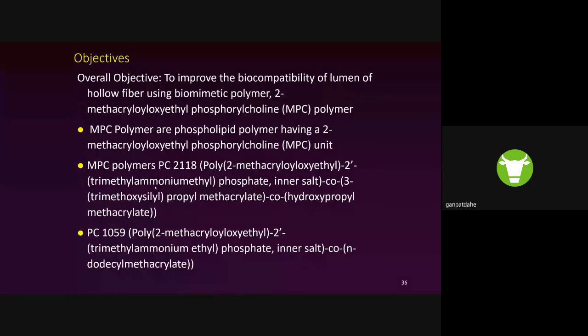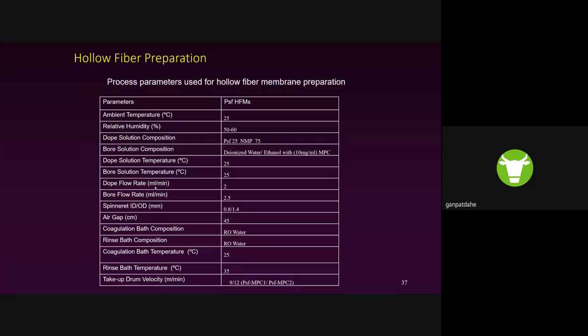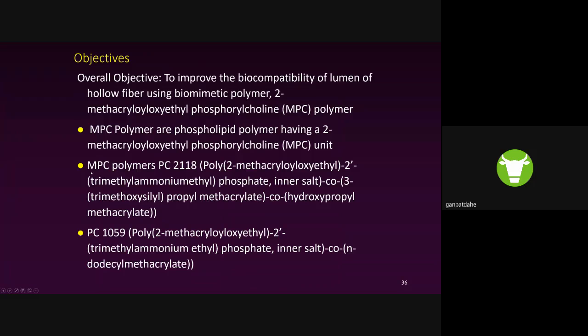As soon as the phase separation happens, this polymer also gets diffused or adheres to the surface of the lumen side of the membrane, and we try to make this in situ coating of the MPC polymer on the lumen side of the hollow fiber. So this is the process parameter we used, and here we make two types of polymers. The names we have given are PSF MPC1 and PSF MPC2, and these are two hollow fibers made from these two different MPC materials.